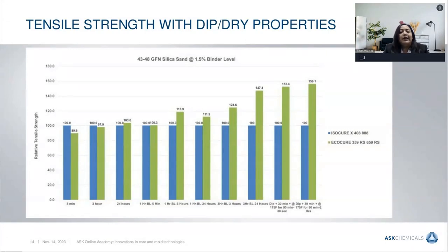This plot highlights one of the key properties of EcoCure 359RS, 659RS. The y-axis of this graph represents the relative tensile strength. The strength of one of the binder systems is normalized at 100 and the values of EcoCure 359RS, 659RS are plotted based on the normalized value of 100. So this clearly indicates the outstanding performance of EcoCure 359RS, 659RS in humidity resistance, bench life, and strength under hot and cold conditions after being treated with water-based coating. So this binder gains almost 50% more strength after being dipped in a water-based coating and being passed through a drying oven.